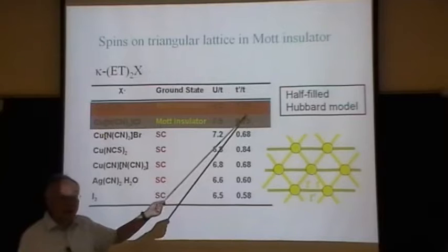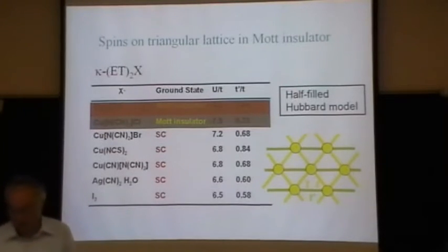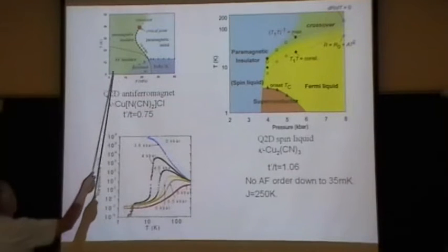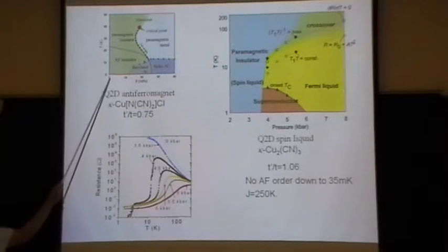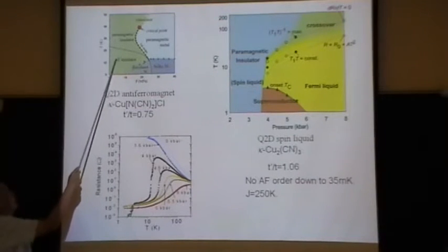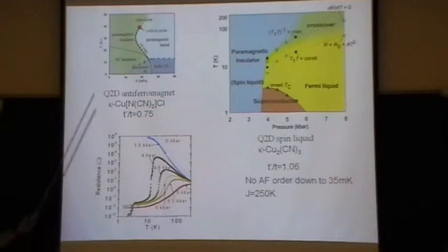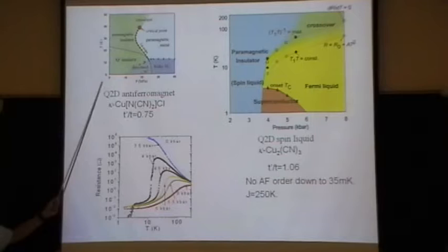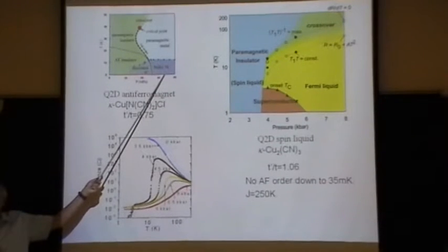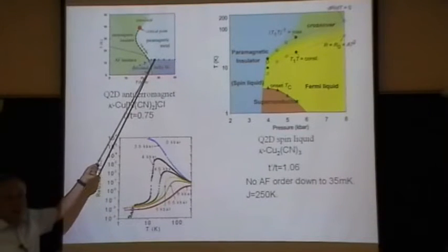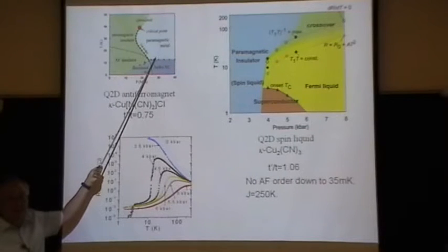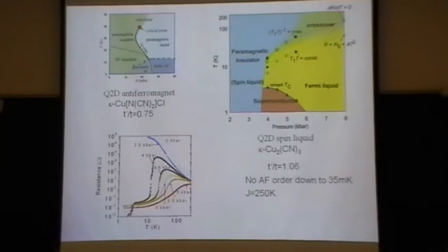But the interesting thing experimentally is that I can tune the anisotropy. If it is anisotropic, you have the more or less conventional phase diagram. So this is one where the P prime is anisotropic. At ambient pressure, you have a Mott insulator, and there's an antiferromagnetic order that then goes away at low temperature. With pressure, amazingly, it turns into a superconductor. This is the highest transition temperature superconductor we know for organics, 12 degrees. And as I would try to argue, 12 degrees for an organic is the same as 120 degrees for a metal. So this is actually a high-Tc superconductor.